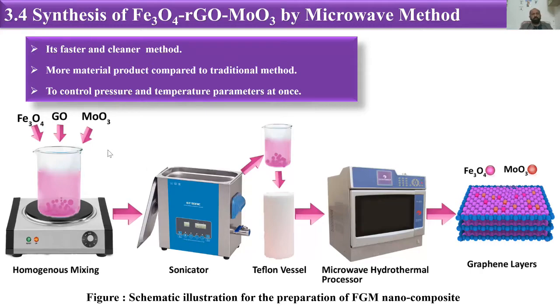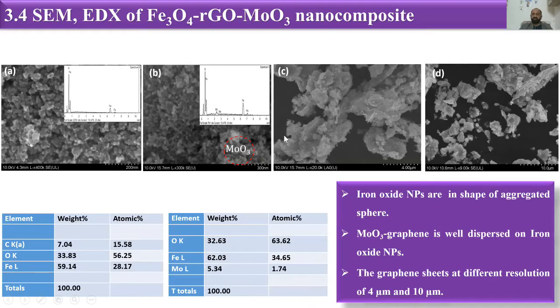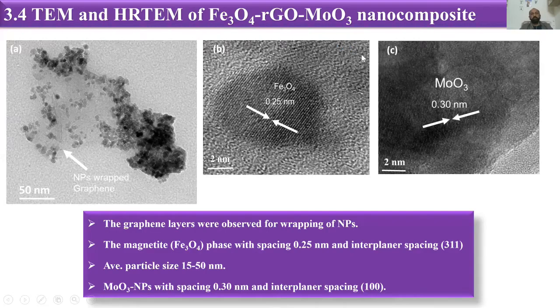Again, we have done SEM for this system, and we have got the MoO3 and graphene layers in our system, and we have the atomic percent and weight percent. We have the iron, oxygen, and Mo values in our system. Then we have done TEM and HRTEM of our system, and we have got the nanomaterials wrapped by the graphene, with iron oxide and MoO3 and the interplanar spacings related with our iron oxide and our MoO3 materials.